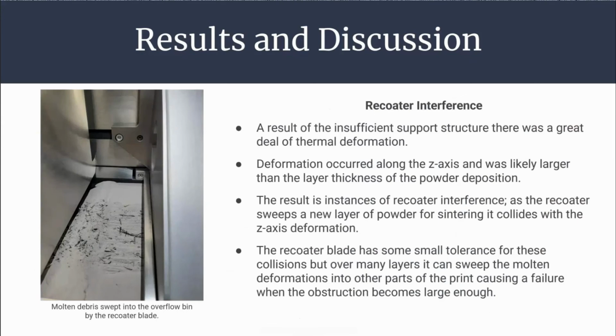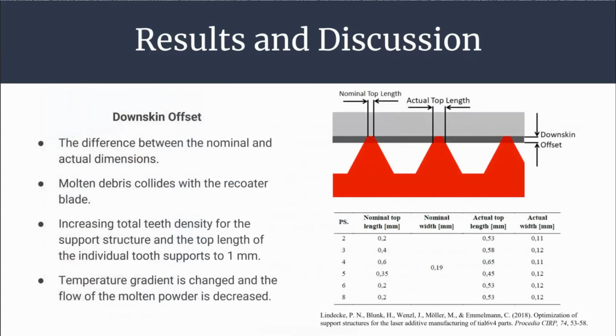So what happens is, as the recoater comes across, it's hitting these deformations. Essentially, the part itself isn't level, and it's interfering along the z-axis with the recoater blade as it tries to sweep a new layer deposition across. And a large part of that was what's known as the downskin offset effect, which is essentially that initial layer between the support structure and the part. Actually, molten powder leaks into the support structure. So you're left with kind of an uneven layer for the part to be built on. And it can affect how the recoater can deposit a fresh layer because it's constantly running into contact or obstructions.